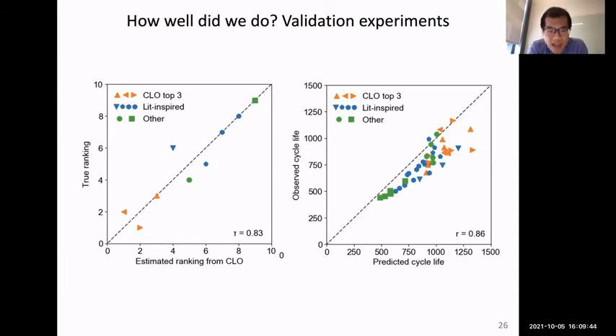We actually went ahead and did the full experiment by cycling the battery to failure. The left plot shows you the true ranking of the top cycling protocols versus the estimated ranking. You can see we got a few of them wrong, but we're not off too much. The right is similar to the plot I showed earlier, which is the observed battery lifetime versus the predicted lifetime. There's a little bit of a bias, but all in all, we're achieving very good predictions. So these validations are giving us hope that we have an opportunity to substantially decrease optimization tasks when it comes to batteries.